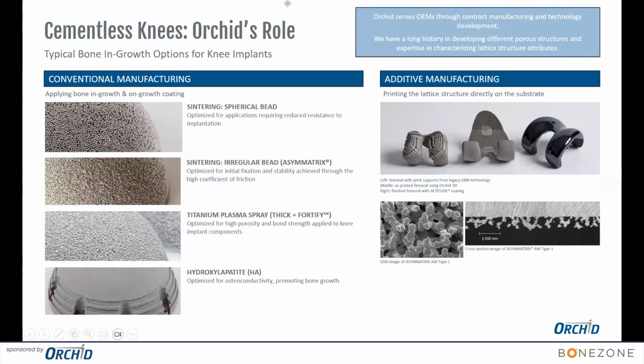An example would be anytime you apply a sintered coating, you're doing heat treatment to do the sintering process at temperatures significantly greater than the beta transus for titanium, where you end up getting incipient melting. So you're going to get a significant amount of grain growth. That grain growth essentially leads to weakened mechanical properties. So fatigue strength decreases, ultimate tensile strength, elongation to break, all of those decrease when you do sintered coatings.